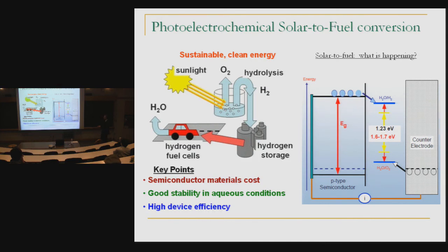So the question is, if you could actually make a system where, for example, in quantum dots, you get quantum confinement in all directions, the relaxation times for the electron-hole pairs are much, much longer than in classical systems. And so you can actually harvest these hot electrons off before you let them relax. In terms of that, I don't see why that shouldn't be possible as long as the energetics of the system make sense. That means that as long as the band gap of the semiconductor is centered around the redox potential of the couple that you're looking at, then the electron hole pair should be pretty uniform about that as well, and you can just harvest that off.